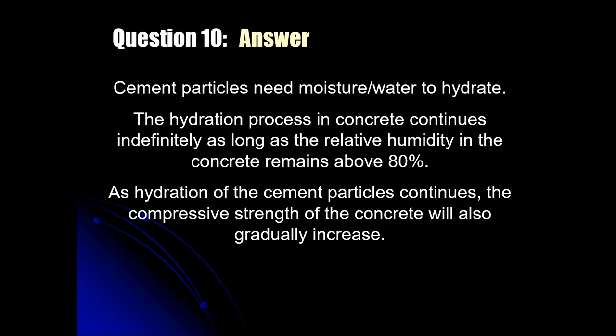My mentor was a wonderful German engineer by the name of Hermann Protz. Prior to the Big Dig in Boston, Hermann Protz was involved in taking cylinders, core samples, out of tunnels that had been constructed, I think, in the 1930s. That concrete went in at about 2,500 PSI. But in the late 80s, early 90s, when Hermann took those cores and had them broken, the PSI was over 7,000. So the compressive strength can continue to increase over time as long as there's sufficient moisture to continue the hydration process.